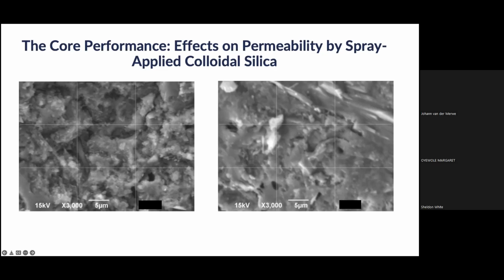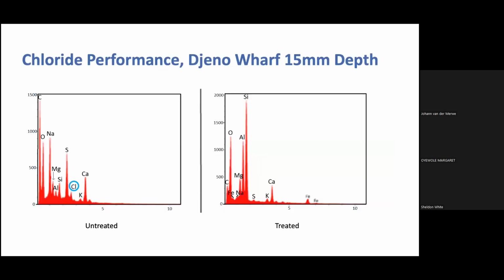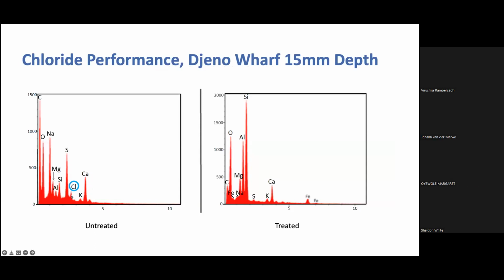Now, this was impressive when we saw these results, but what was more impressive was this. At the 15 millimeter depth, the untreated specimen had a pretty significant chloride peak after only 2 years in the ocean. The treated specimen showed no chlorides. This was done by X-ray spectroscopy by an independent laboratory, demonstrating that the chloride movement was restricted.